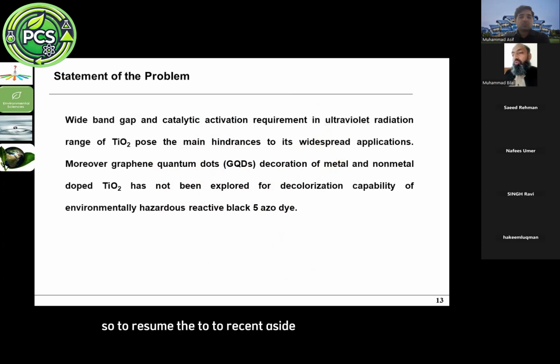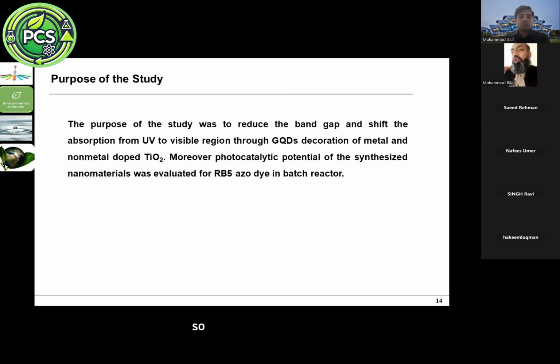To summarize the problem, the wide band gap and the catalytic activation requirement in the ultraviolet radiation range pose the main hindrances to the widespread application of titania. Moreover, graphene quantum dot decoration of metal and non-metal doped titania has not been explored for the decolorization of environmentally hazardous reactive black 5 azo dye. So the purpose of this study was to reduce the band gap and shift the absorption region from UV to visible through graphene quantum dot decoration of metal and non-metal doped titania. Moreover, the photocatalytic potential of the synthesized nanomaterial was evaluated for reactive black 5 azo dye in a batch reactor.